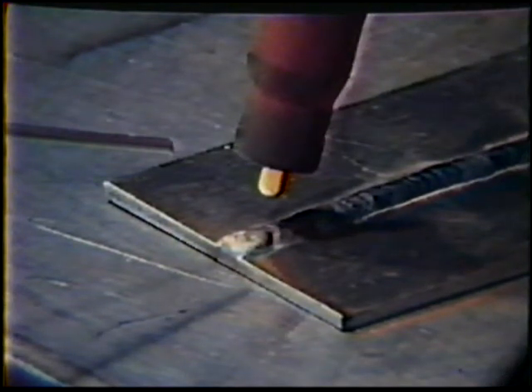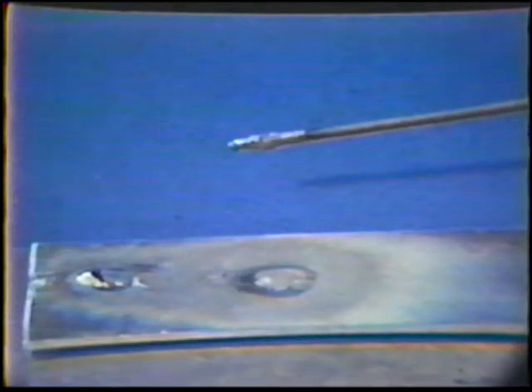When depositing the weld bead, be careful not to push the filler metal too far into the puddle, touching the rod against the tungsten, or touching the tungsten to the puddle. This will cause tungsten contamination. If this happens, regrind and ball the tungsten.